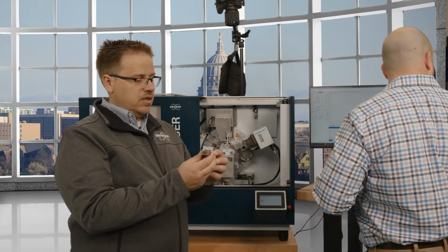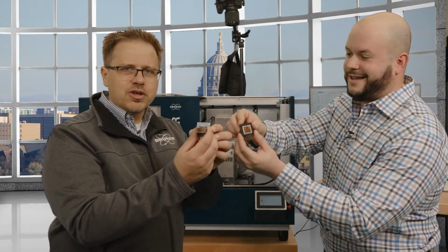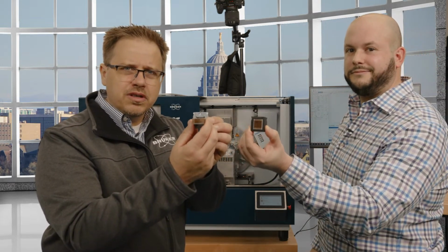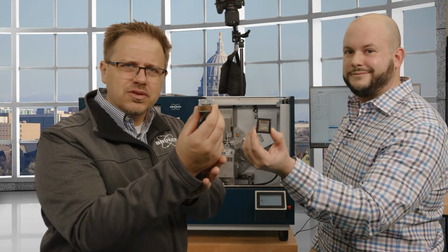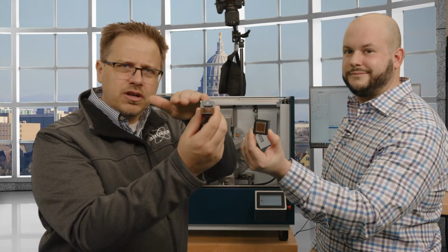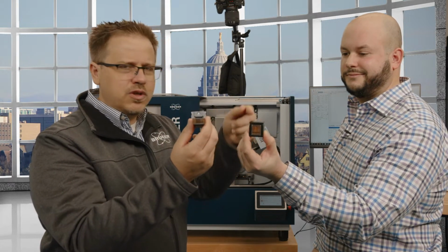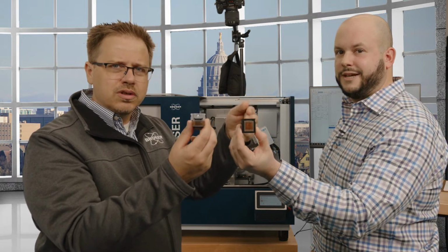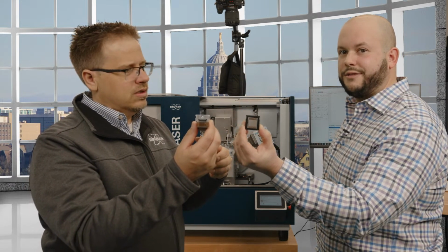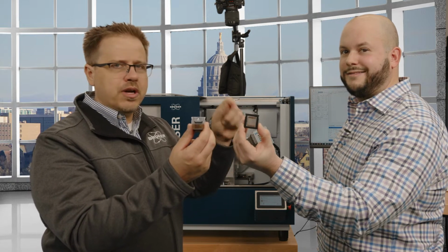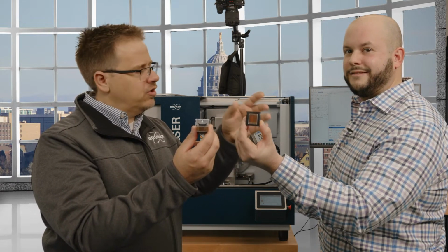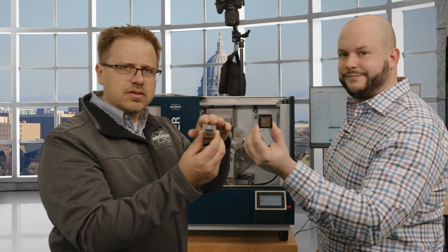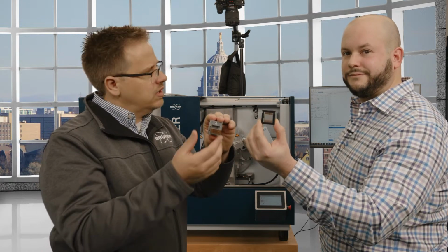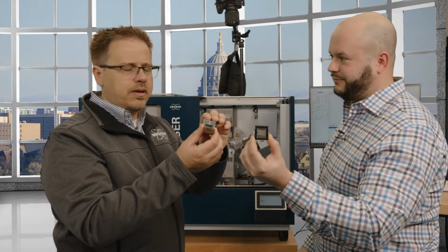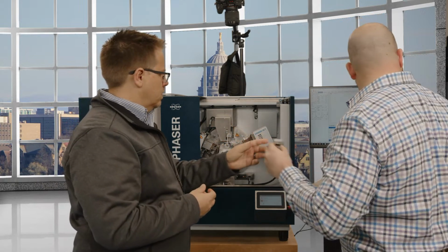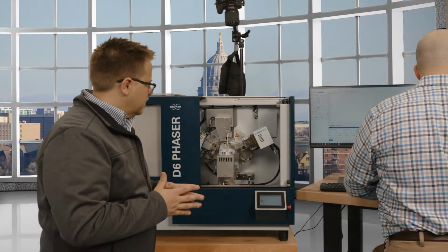Yeah, so to give you guys an idea how these work, maybe if you grab that one. So if we hold this up here and I tilt it up and down, sometimes I think you can see through it, but the fins are this way, horizontal. The fins here, on the other hand, those are vertical. Yep, see that if I go left and right, you can see through, now you can't. So that gives you a better resolution for the powder diffraction, things like that. This, on the other hand, gives you the insensitivity to any height issues, things like that. Exactly. Or broadening of the signal across the sample surface.